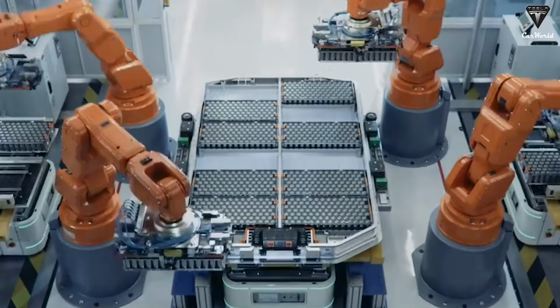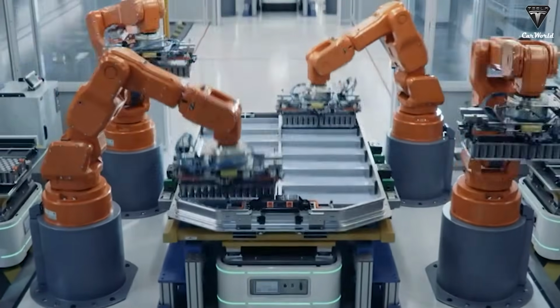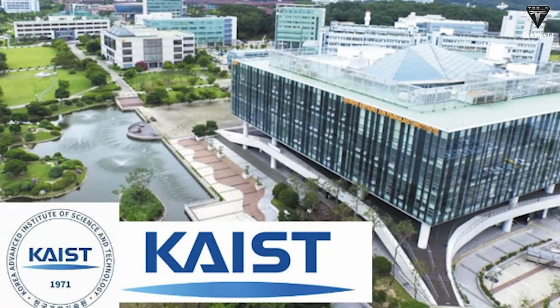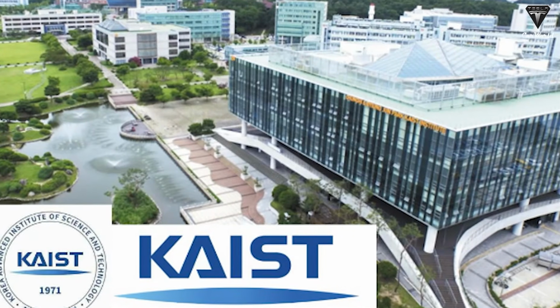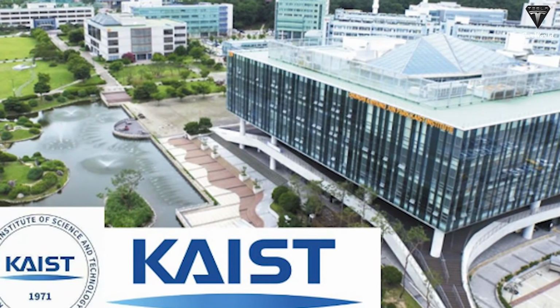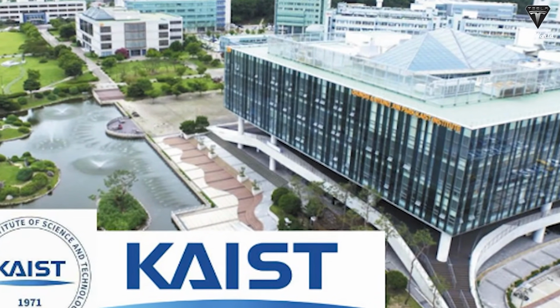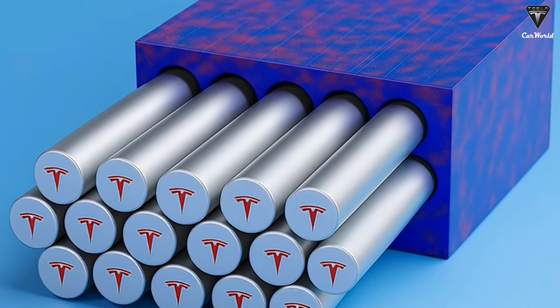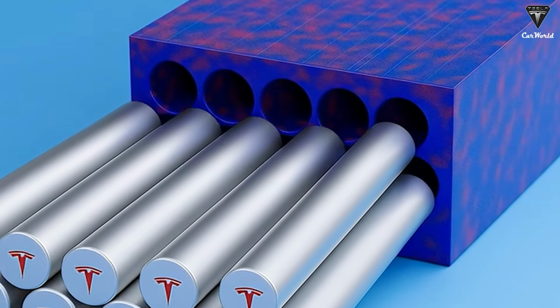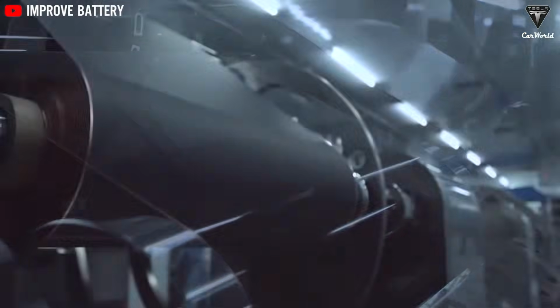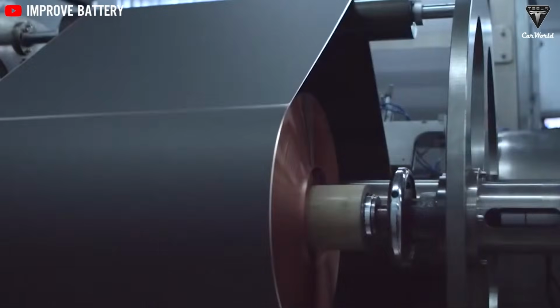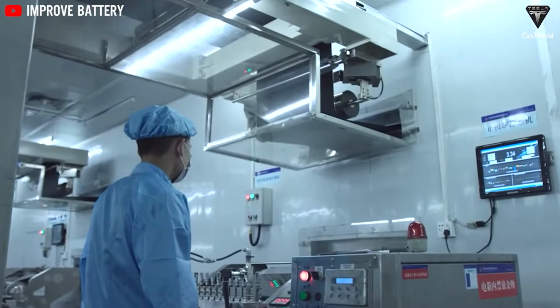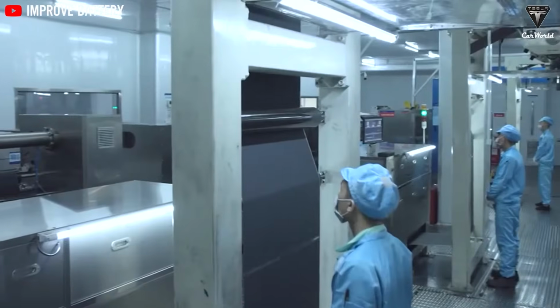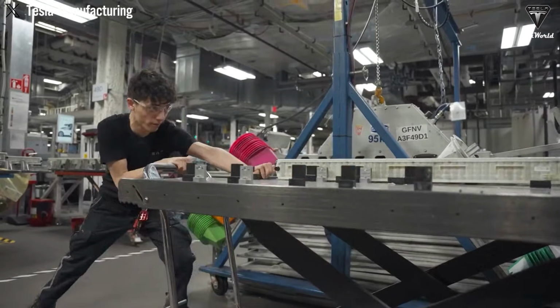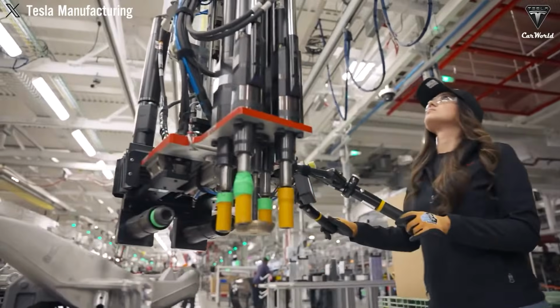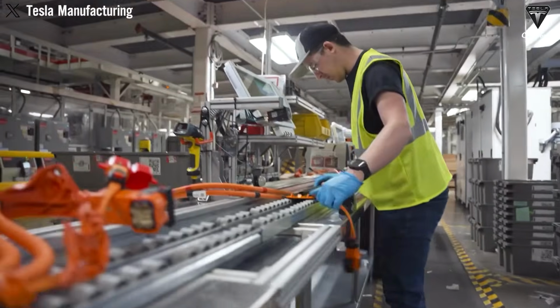The one at Korea Advanced Institute of Science and Technology, KAIST, which has developed a high-density structural battery made from a multifunctional carbon fiber composite. Their innovation lies not only in materials selection, carbon fiber for strength, and solid polymer electrolyte for ion conductivity, but also in the process of integrating those materials. Resin, a core component of the composite, typically traps air during curing, weakening both structural and electrochemical performance.